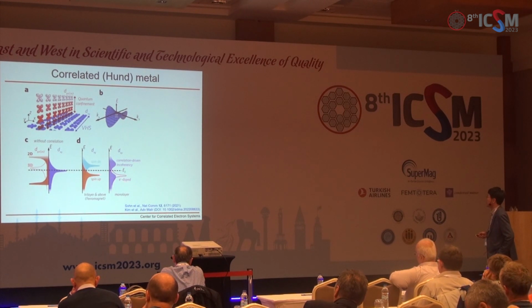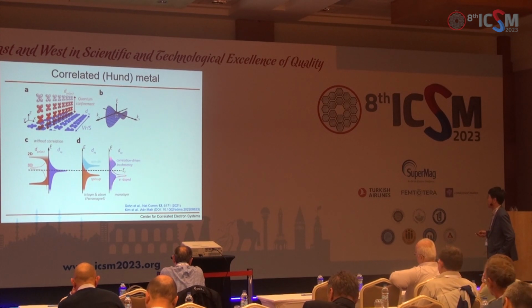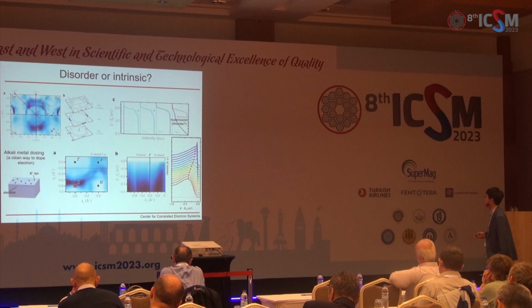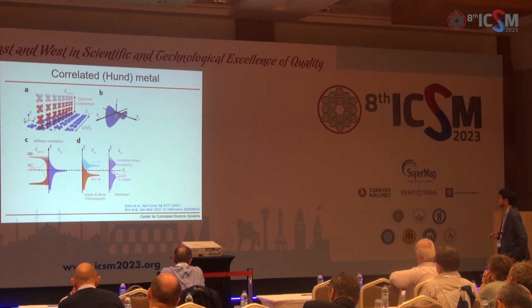Now, once we dope electrons, this density of states goes down, then we don't need this Mott transition because the density of states is already low, and that's what we see. The van Hove singularity moves away from Fermi level, and this quasi-particle is restored.